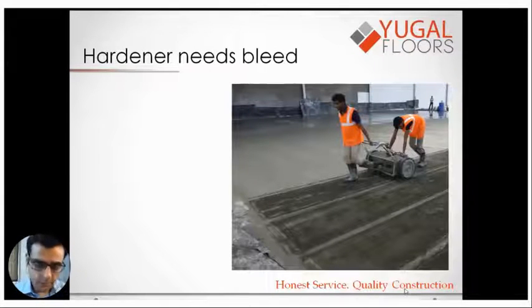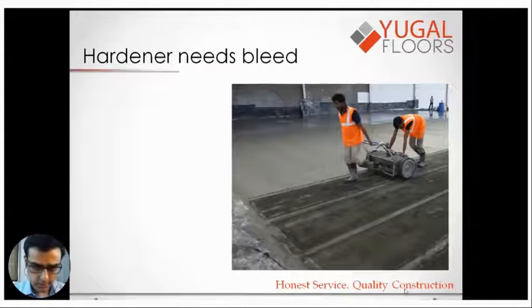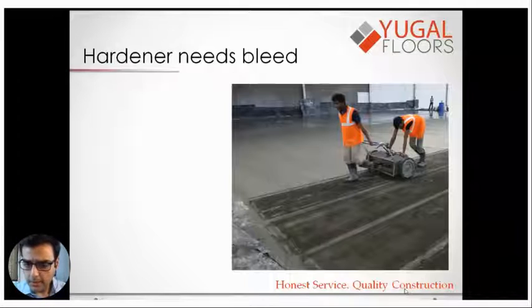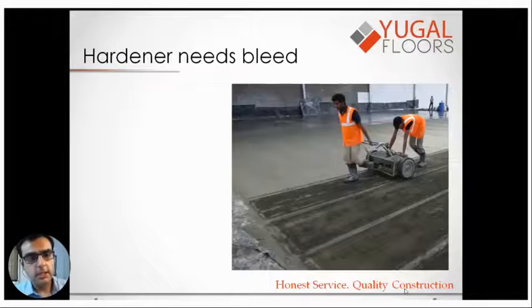Hardener also needs bleed. Rama is going to talk in fair detail about hardener in his presentation, so I'll just touch upon it briefly. Hardener is nothing but a mix of stone and cement and some dispersants in a dry form. So when we apply hardener on the floor, we need to wet it. And the way we wet it is we use concrete's own bleed to wet the hardener. So in the photograph, you can see two shades of gray. The darker shade is one that has already been organically wetted by the bleed from the concrete. The lighter gray is still absorbing water from the surface.